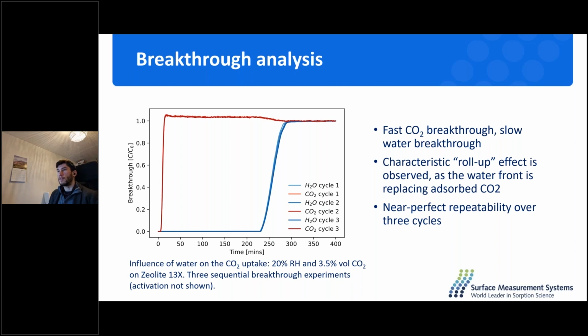So these are 3 breakthrough curves, also on a zeolite 13X. We see CO2 breaks through quite early, while water takes longer to break through. Again, it shows that there is much more affinity for water. Just as a side note, this is at 20% RH and 3.5% by volume CO2. There is very good repeatability between cycles.